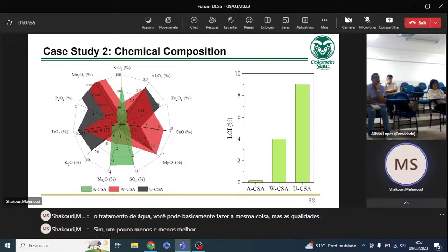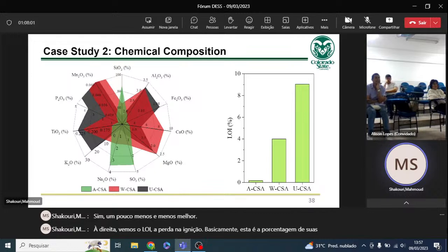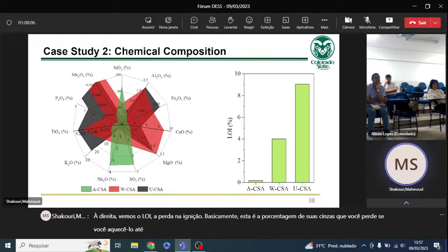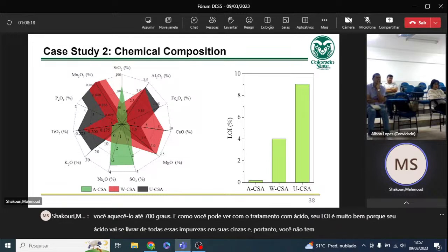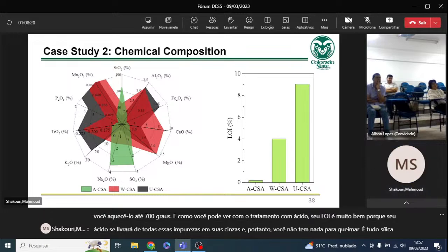On the right, we see the LOI, the loss on ignition. Basically, this is the percentage of your ash that you lose if you heat it up to 700 degrees. As you can see, with acid treatment, your LOI is pretty low because your acid will get rid of all those impurities in your ash. So you don't have anything to burn. It's all silica, and silica does not really burn.